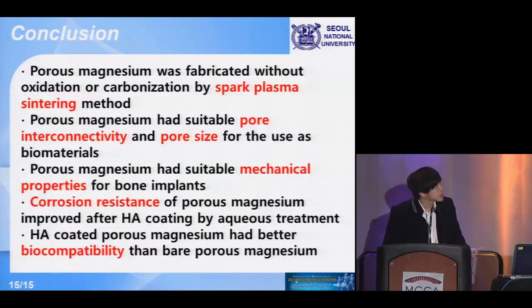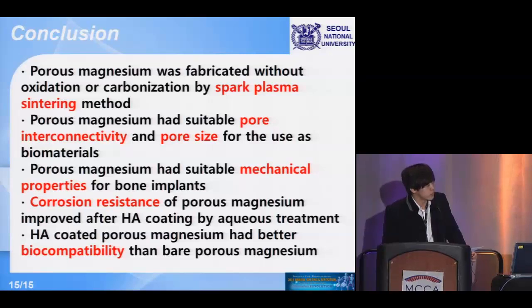And for the conclusions, porous magnesium was fabricated without oxidation or carbonization by the spark plasma sintering method. And porous magnesium has suitable pore size, interconnectivity and mechanical properties for bone implants. And corrosion resistance of porous magnesium improved after hydroxyapatite coating by aqueous treatment, and biocompatibility has also been improved.